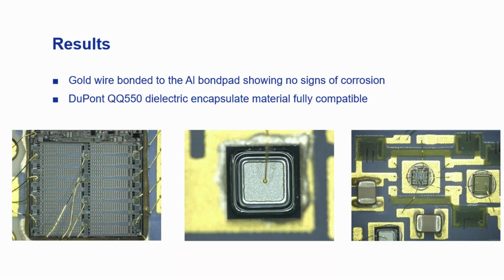It was a very critical customer, and they had high product and high requirements. So we decided to focus on multi-testing of different cleaning chemistries, and we were able to narrow down to a pH neutral formulation, which was able to successfully remove the flux residues, as well as add enough corrosion inhibitors in its formulation, which was able to completely avoid the formation of galvanic corrosion related failures. So this process eventually was subjected to several qualification and verification tests and was finally implemented at the customer site, and the clean substrates were later subjected to electrical testing, which finally was able to meet the customer's requirements, and the process was successfully implemented.